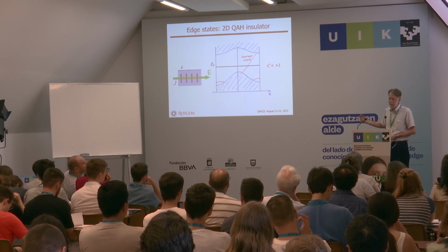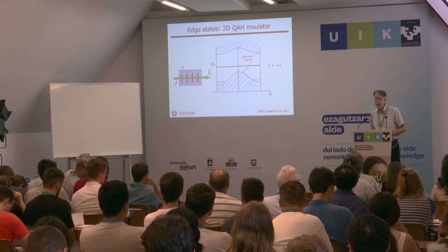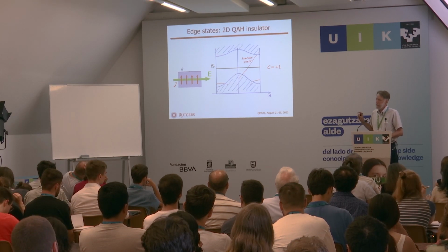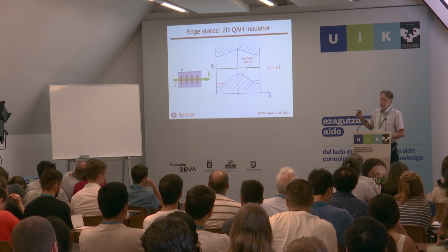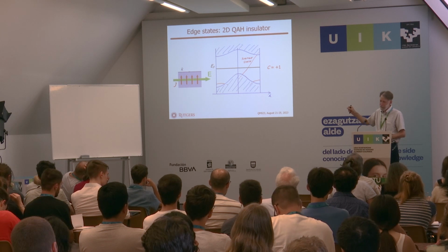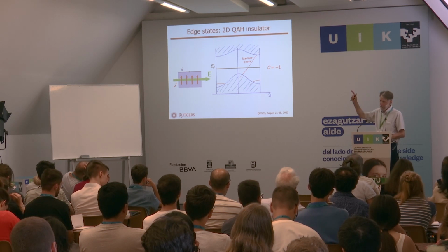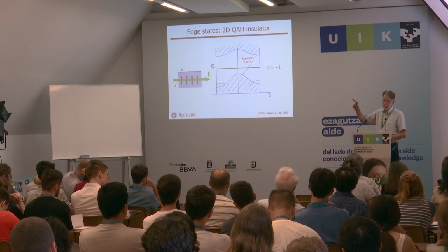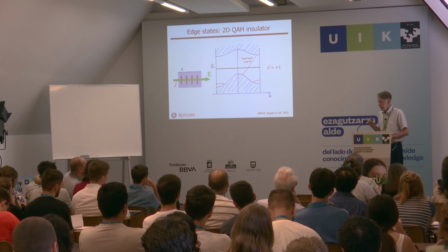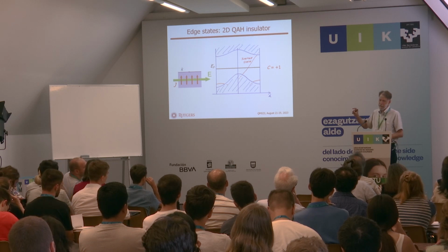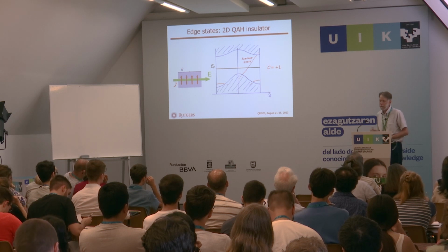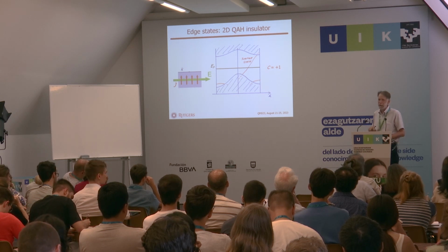in the world of spin-orbit driven topological insulators, in order for the material to be topological, it should be the case that if you turn the spin-orbit coupling from its full value to zero continuously, a gap will close and then reopen, because by the time you turn the spin-orbit coupling to zero, it can't be topological. And so that means that the gap has to be on the order of the spin-orbit coupling or less. So let's say on the order of 200 millielectron volts or something.